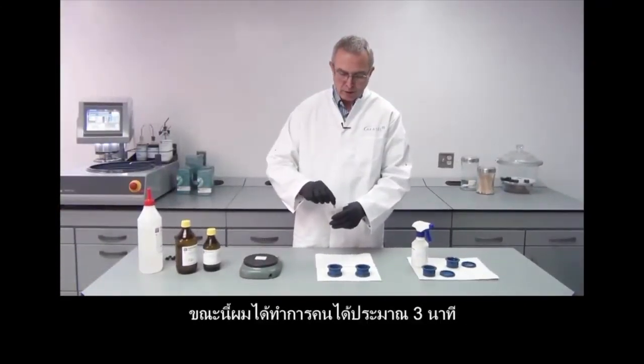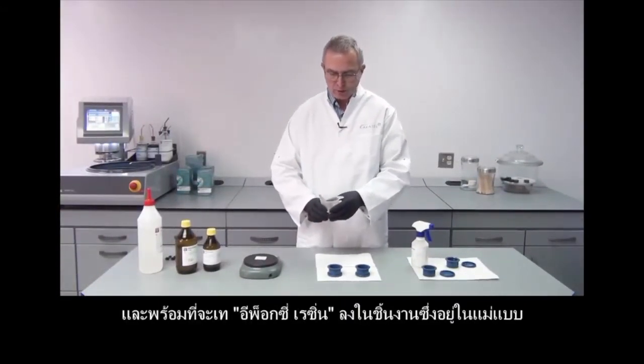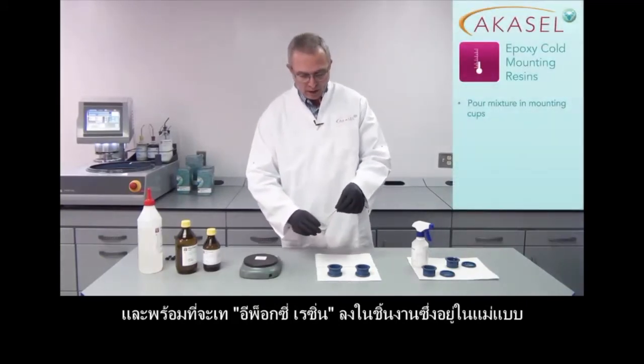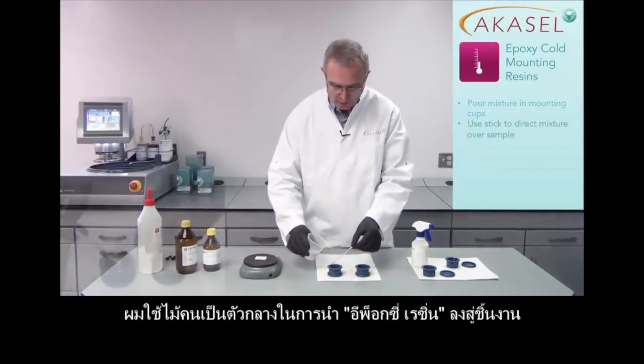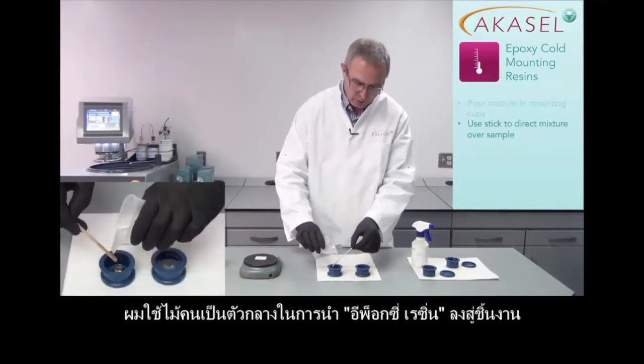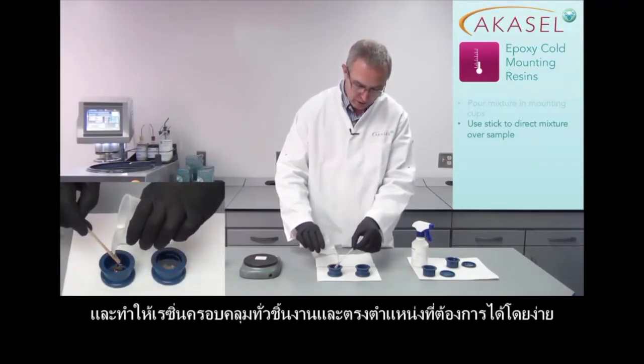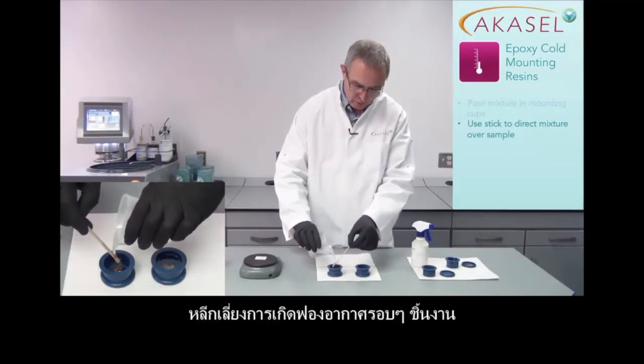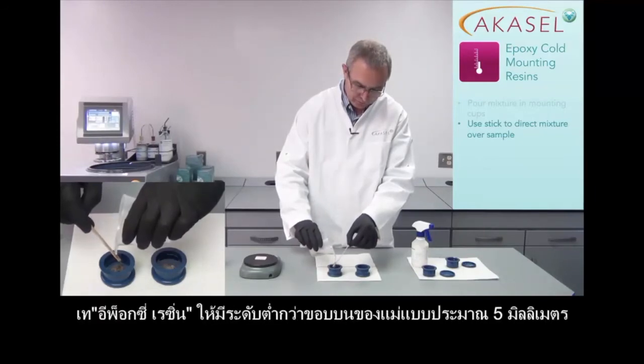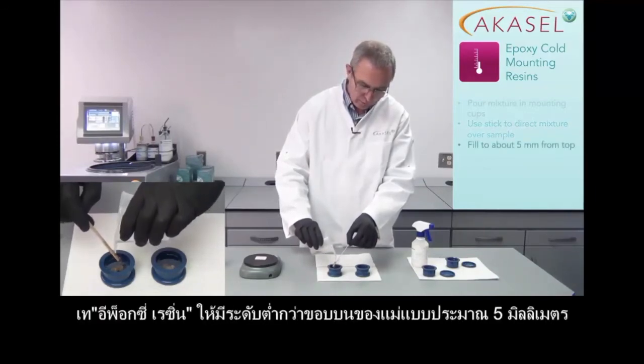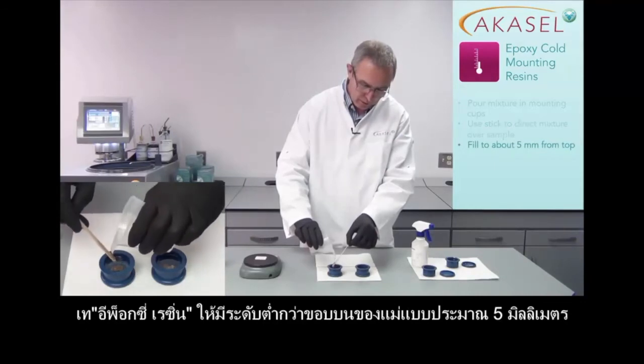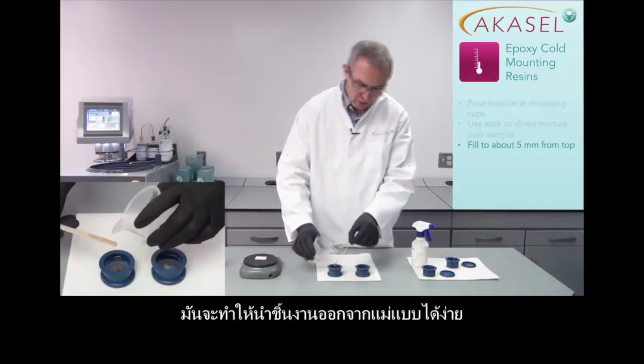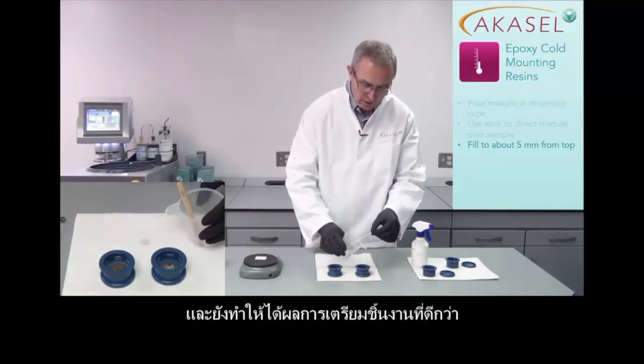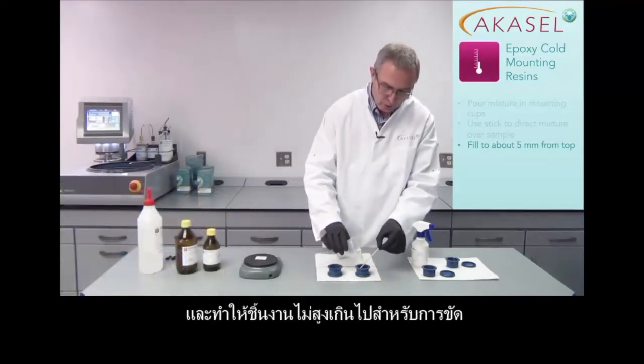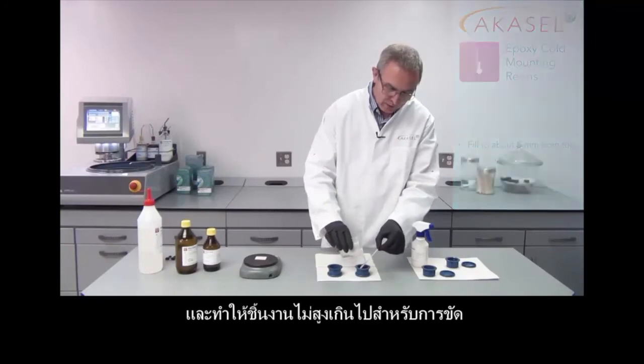Now I've been mixing thoroughly for 3 minutes, and I'm ready to pour the mixture into the mounting cups. I use my mixing stick to direct the mixed resin onto the sample. That makes it easier to cover the sample correctly, and it will also avoid trapping air bubbles around the sample. I'm only going to fill the mounting cups to about 5 millimeters from the top. That makes it easier to remove them, and it will also make the preparation results better, because the samples should not be too high when grinding to avoid penciling.